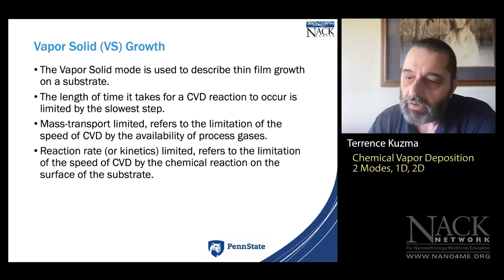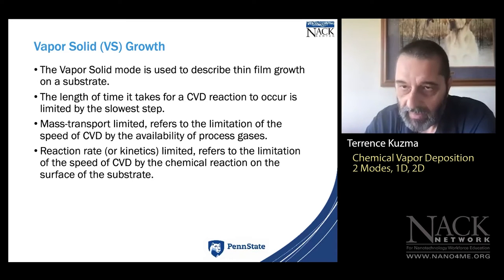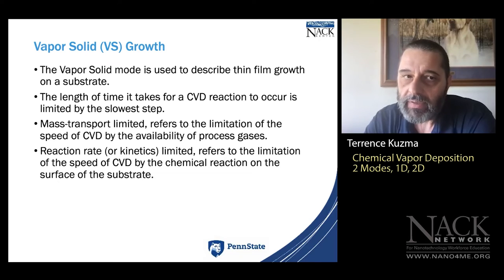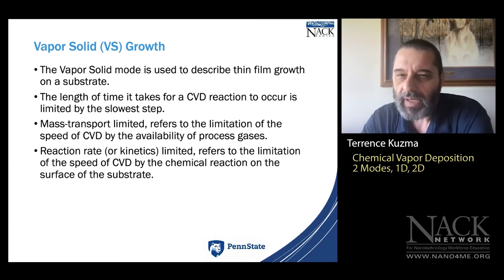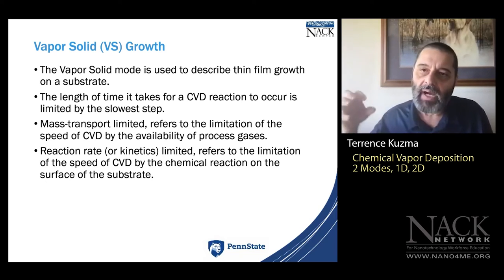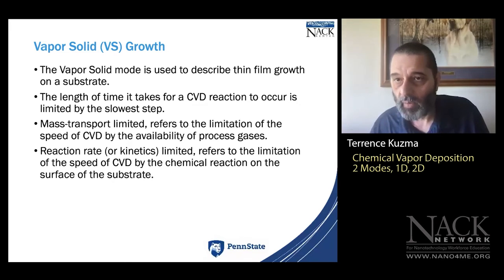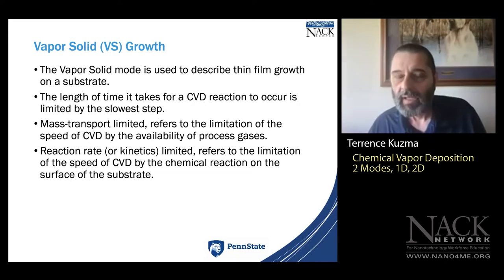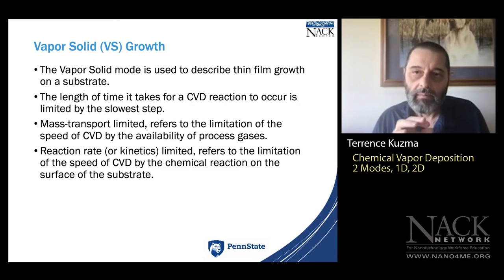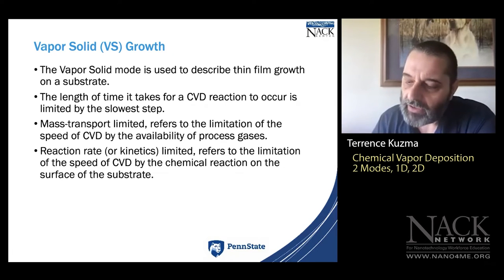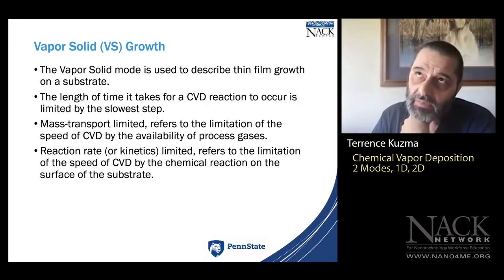For the 2D VS vapor-to-solid growth system, the reaction time can be thought of in two ways: limited by available gas — that's mass transport — or limited by the reaction kinetics, which is driven by heat or available energy. So the two rates of reaction are mass transport limited and kinetics limited.